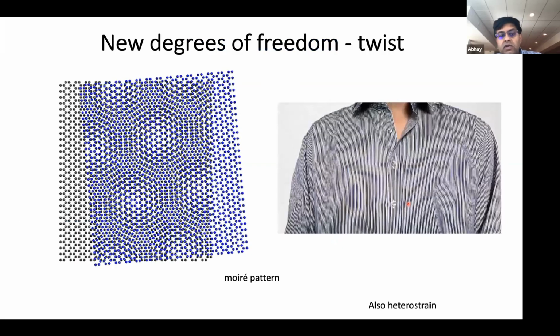Okay, so I'm going to talk about 2 degrees of freedom, and one of these is the twist degree of freedom. What this is basically, I take 2 sheets, which are both monolayers, and you twist one sheet relative to the other by some angle and produce a material. This is a cartoon version of that for 2 sheets of graphene. When you do this kind of twist operation, you produce a superstructure that's much longer than either of the atomic periodicities. And the wavelength of the superstructure is simply given by the difference in wave numbers of the 2 lattice vectors involved.